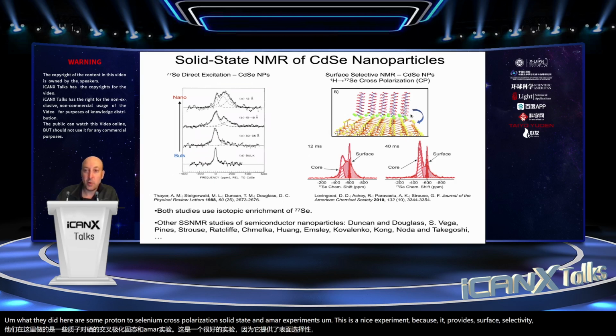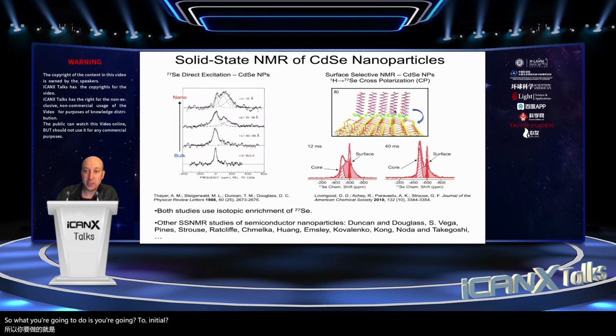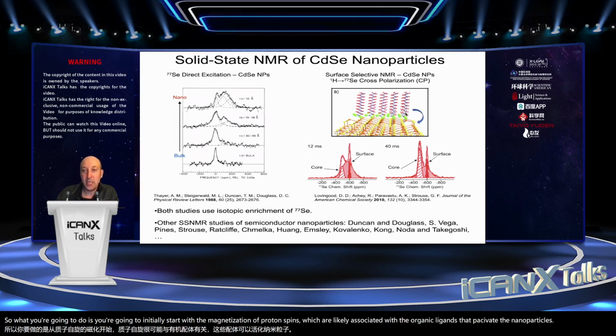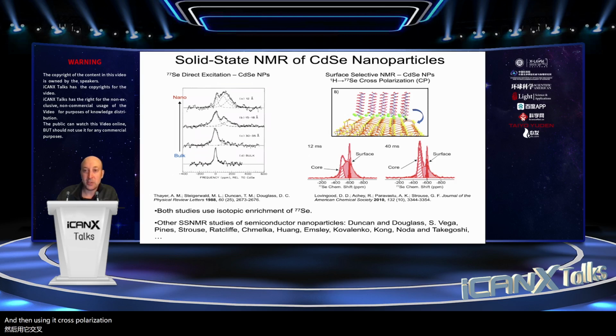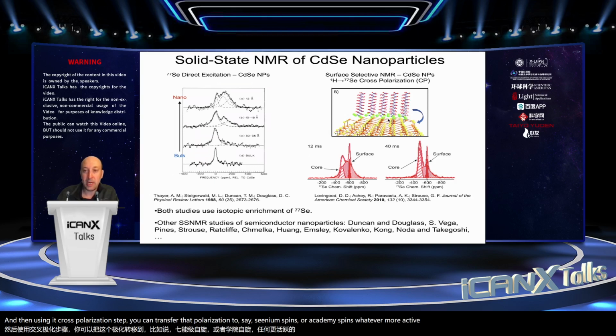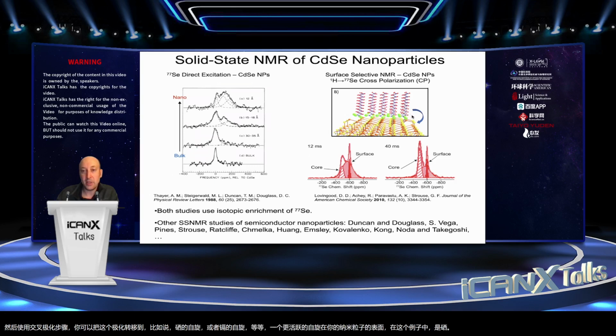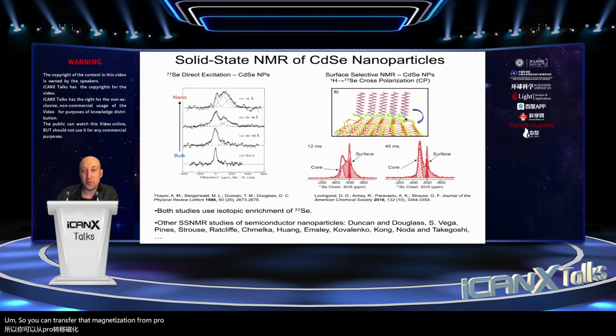So what you're going to do is initially start with the magnetization of proton spins, which are likely associated with the organic ligands that passivate the nanoparticles. Then, using a cross-polarization step, you can transfer that polarization to, say, selenium spins or cadmium spins, whatever NMR active spin is on the surface of your nanoparticle. In this case, it was selenium. So you can transfer that magnetization from protons to selenium spins that are within a few angstroms of the surface.